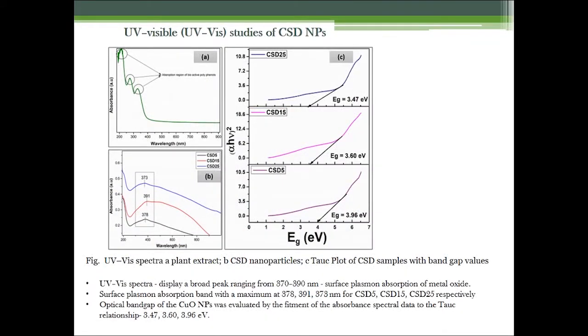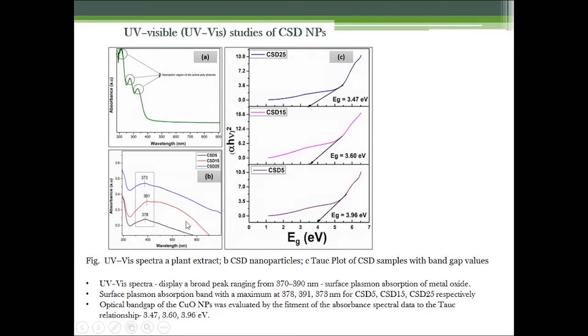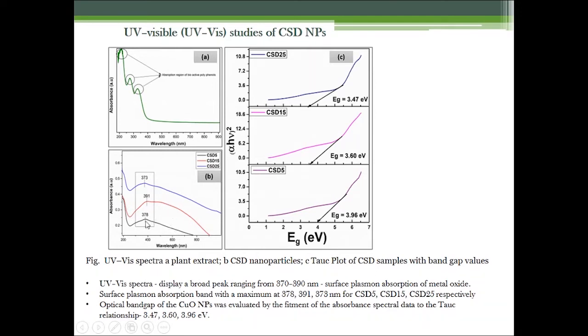Coming to the UV visible spectral studies of the copper oxide nanoparticles. The optical properties of the sponge-like porous nanostructures were determined by UV visible absorbance spectroscopy. UV visible spectra display a broad peak ranging from 370 to 390 nanometer, which is due to the surface plasmon absorption of metal oxide. The metal oxides exhibit surface plasmon absorption, which can be attributed to the collective oscillation of the free conduction band electrons, which get excited due to the incident electromagnetic radiation.